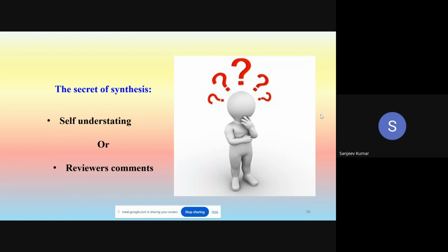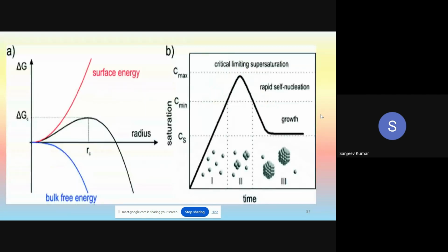Now, what is the secret of synthesis? How much extract you need, how much time you need to give the reaction. Sometimes it depends on self-understanding, sometimes on what the paper or the reviewers' comments demand. The peak shows a critical reaction time and a critical concentration of the precursor. When you achieve this concentration, this peak will happen. Whenever this peak happens, the nanoparticle will start forming.